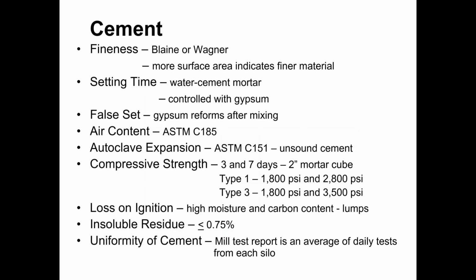All right, there's a phenomenon that can occur in concrete mixing that's called false set. False set is when the gypsum that's been added to the cement reforms into a solid during the mixing process. And this looks like a stiffening or a hardening of the concrete, but it is not. It's just a material transformation of the gypsum going from a liquid state to a solid state. And so that's why we call it a false set. It's not an actual set resulting from the reaction between the cement and the water. The good thing about a false set is that if you keep adding energy, you keep mixing the concrete, that would usually reverse the false set and your slump will come back and you can use that concrete in your project. You don't have to throw that concrete away.